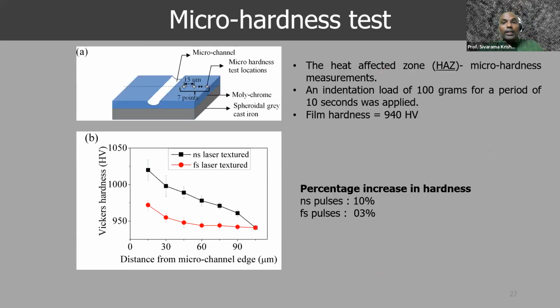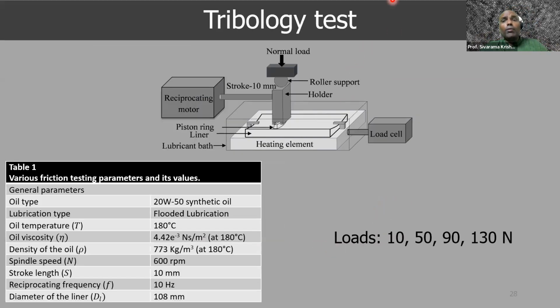And is that so? We first wanted to test the hardness of the regions where we use laser pulses and see if there is some kind of hardening taking place because of melting and reforming and so on. In Vickers hardness test measurements, we figured that the percentage increase in hardness is 3 times higher in the case of nanosecond pulses than femtosecond pulses on average. So this tells us that the femtosecond pulses are not so damaging, although they do the extrusion of materials very well. But really, what we care about is tribological properties.